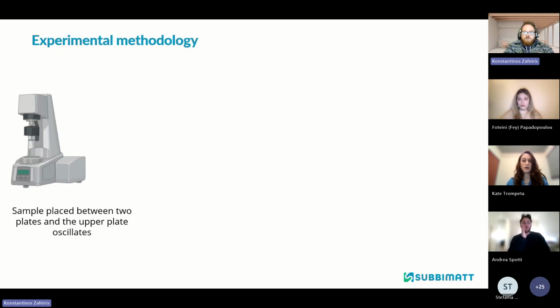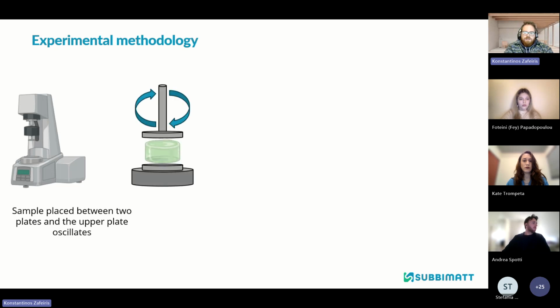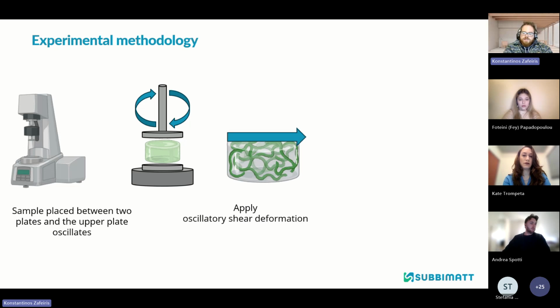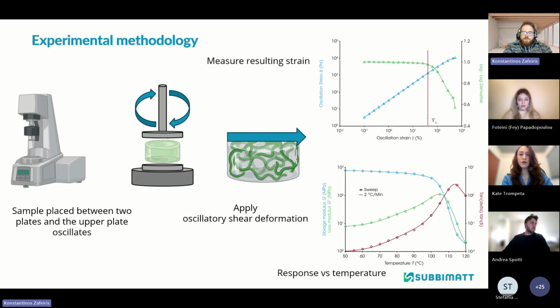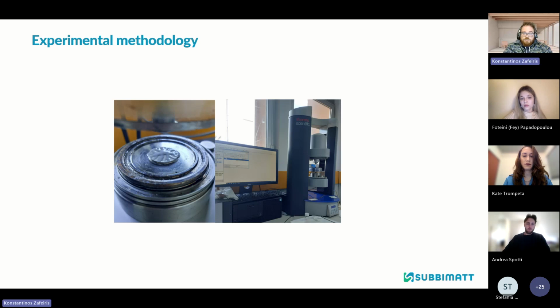In our experiments, we use a plate-to-plate geometry. The hydrogel sample is placed between two parallel plates, and the upper plate applies a small oscillatory motion. This creates a shear deformation in the material, and the instrument measures the resulting stress response. By controlling parameters such as strain, frequency, and temperature, we can probe the material in different conditions. From this response, we extract the storage and loss moduli, which describe the mechanical behavior of the hydrogel. As you may understand, rheology is critical at this point to assess our formulation, and at NTUA, the rheological measurements allowed us to determine the transition temperature, monitor gelation behavior, and evaluate the viscoelastic properties.